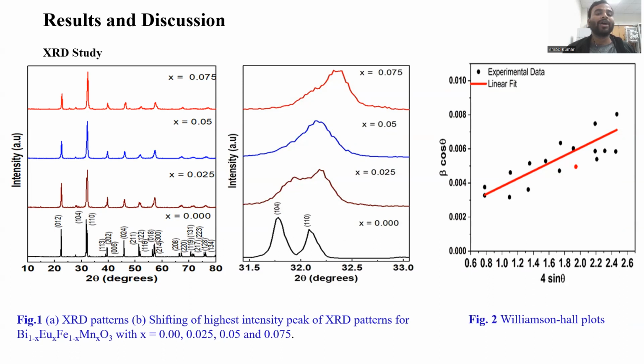So how do I know it's due to the phase change? Previously, I told you about the Rietveld refinement. I did the Rietveld refinement of each XRD pattern, and it confirmed that the phase changes. The space group of the BFO is R3C.